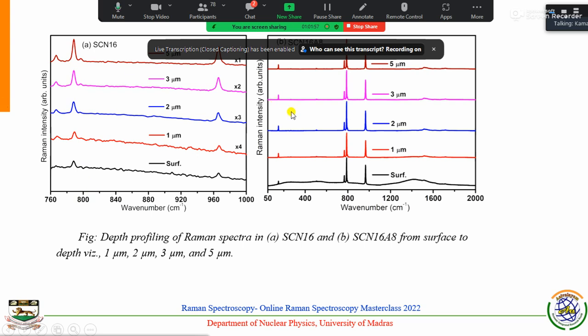Okay, so after annealing, you can see here at the surface region the amorphous peaks are still there because of the accumulation of the defects. But if you approach 1 micrometer, 2 micrometer, the intensity tremendously increases. At 5 micrometer, because it is an undamaged region, of course the intensity is equal to the pristine value, which means the undamaged values are almost equal.